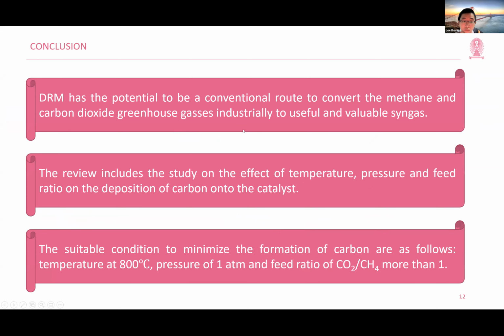the DRM process has a high potential to reduce the two major greenhouse gases, which are methane and carbon dioxide, to useful and valuable syngas. To conclude the review, the study on the effect of temperature, pressure, and feed ratio on the deposition of carbon on the catalyst. The general rule of thumb that we have found out is the temperature should be around 800 degrees and above, the pressure around 1 atm, and the feed ratio should be more than 1 for the current catalyst that is being tested.